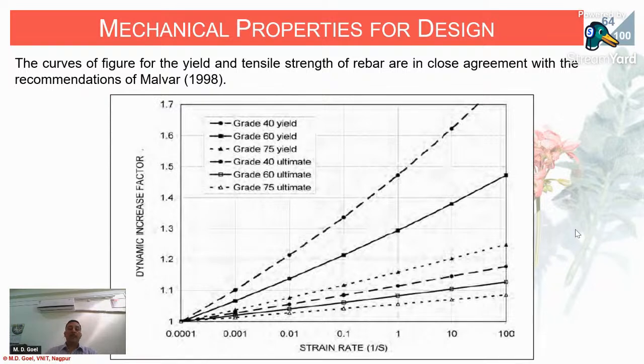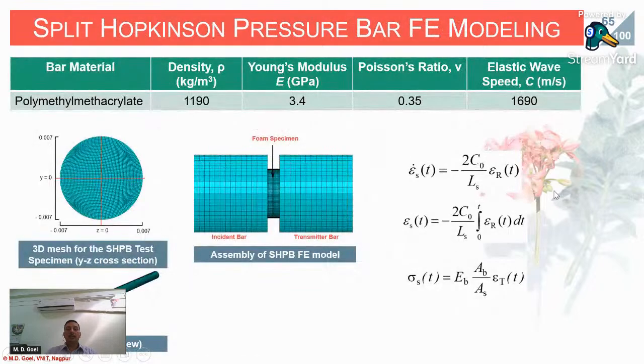Now let us say we have yield strength, where this data is taken from American steel, and tensile strength of the rebar presented by Malvar in 1998. So grade 40, grade 60, grade 75, and so on. With respect to strain rate, he has given values up to 100 per second. So you can directly use these charts to find the dynamic increase factors. Once your dynamic strength is increased, definitely you are going to get a lesser area of steel.